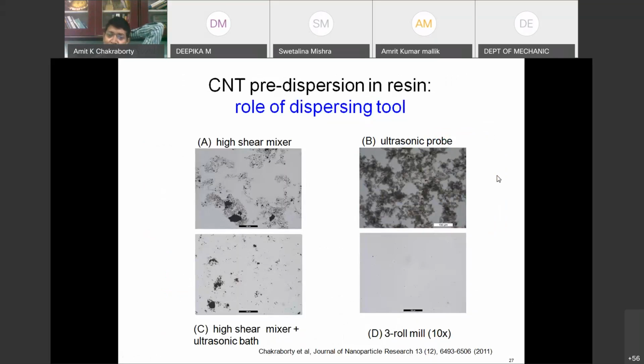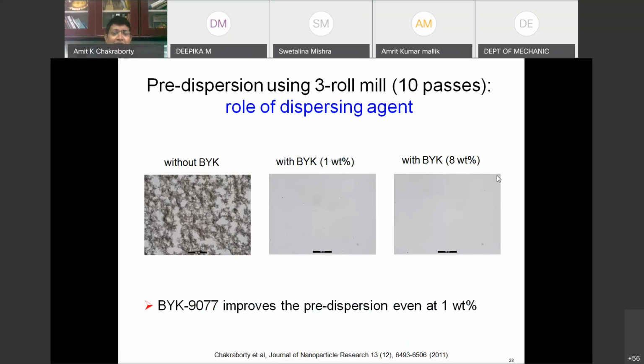Now I was hoping that if I have a very good dispersion, then definitely my product will be very good, and I will have improvement in the mechanical property. But when we tested the mechanical property, we still did not see any improvement. Why? To investigate that, we also chemically modified the surface of the CNTs. First, you see this slide is without BYK. BYK is basically a chemical modifier called a dispersing agent, which helps to disperse the particles.